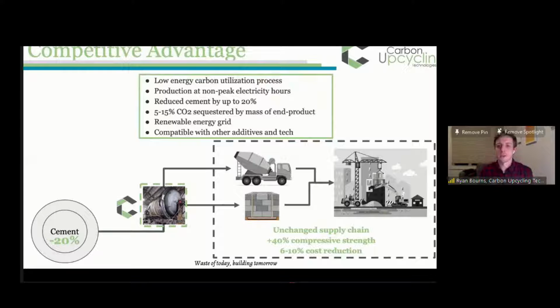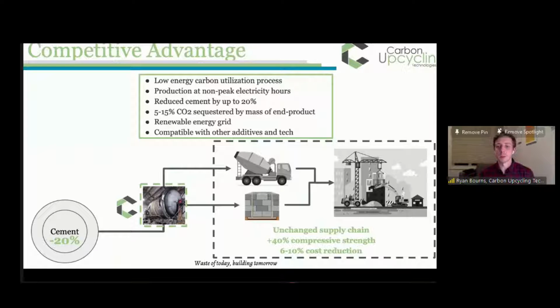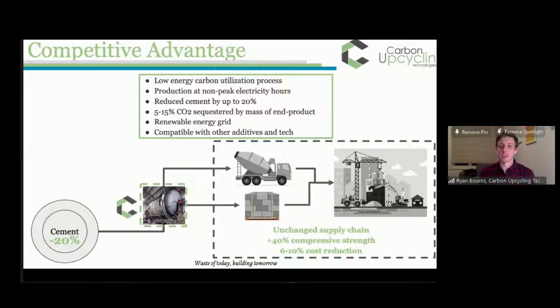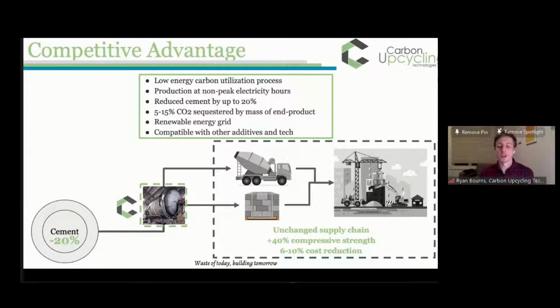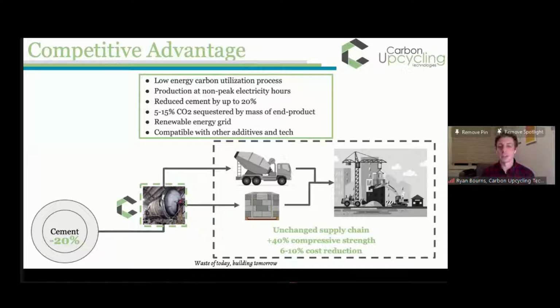And so just to give a bit more clarity to our process and what it can actually do, it's a very low energy carbon utilization process. We're using the full CO2 molecule, so we're not breaking the carbon and oxygen bonds when utilizing CO2. We're just putting it into a pressurized vessel, actually the vessel is right there, that creates both that agitation and necessary environment to facilitate that carbon absorption by that fly ash. This has allowed us to show that we can reduce cement by up to 20% in a standard mix.